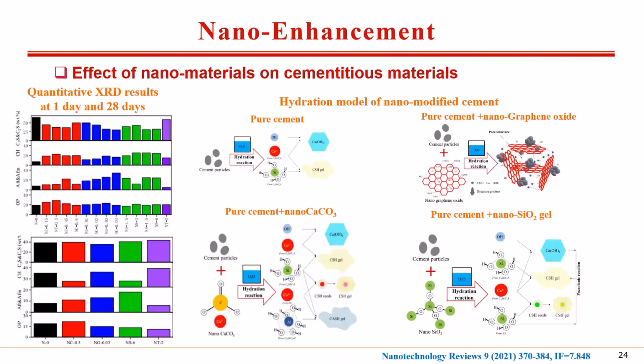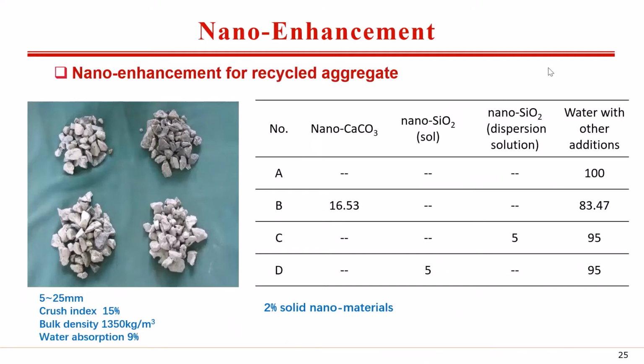And also, we conducted quantitative XRD experiments to find the change of composition and the content of minerals in clinker and hydration products. We can find this is quite different for different nanomaterials. Then we proposed the hydration model of nano-modified cement. Based on those research, we start to use nanomaterials to strengthen the recycled aggregate. 3 different nanoslurries were used in this experiment, and the total solid content of nanomaterials is 2%.